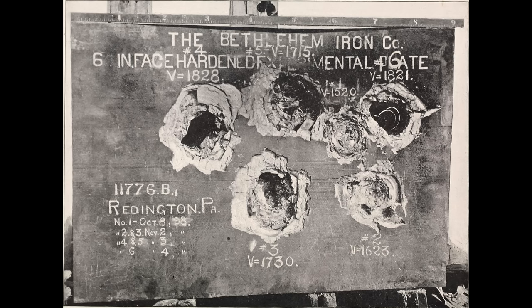Now, when it comes to armour, that would seem to indicate that a harder, brittle material is better, because obviously you want to keep shot out. A softer, more ductile material, like, say, wood, might not fail spectacularly in the way that some of the iron plates were, but it would let in pretty much almost any heavy-grade shot you sent at it, which rather defeated the point of it being armour.